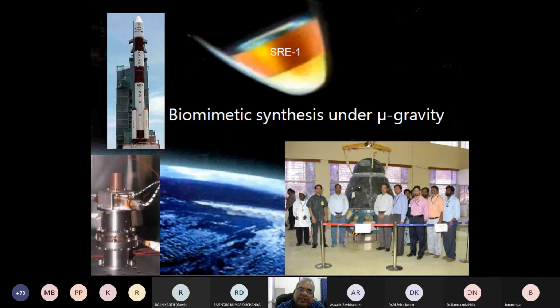So they launched an unmanned space vehicle in 2007, and there I got the opportunity to develop a payload to carry out biomimetic synthesis under microgravity and see what difference we notice in the hydroxyapatite grown in the lab and in microgravity. There were two reasons. Whatever we were doing, we were not able to reduce the size of hydroxyapatite or calcium phosphate crystals to less than 80 nanometers on the ground in our lab.